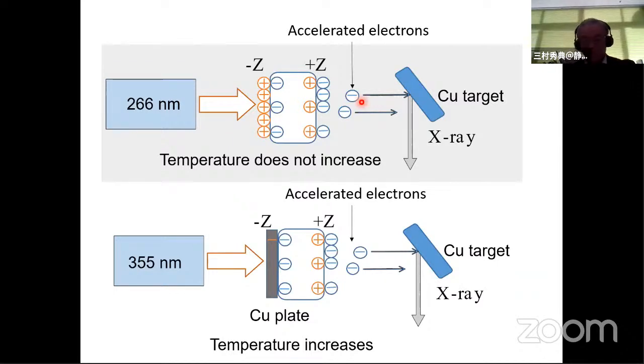From these results, we speculated the electron emission mechanism. When we excited the lithium niobate crystal with 266 nanometer UV light, electron emission is not due to the thermal effect. The absorbed UV light generates electron hole pairs in the lithium niobate crystal, and these electron hole pairs decrease the polarization in the lithium niobate crystal, but the detailed mechanism is not clear. On the other hand, in the case that we excited the lithium niobate with the copper plate using the 355 nanometer UV light, electron emission and the generation of X-rays is a thermal effect.